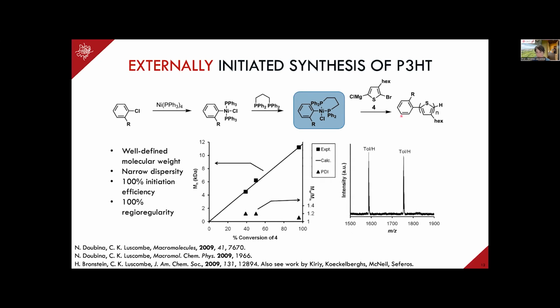And this allows us to really synthesize polymers such as P3HT in an extremely controlled way. So the benefits of doing this polymerization is that we end up with very well-defined molecular weights. If we target a specific molecular weight, we can obtain it. And this is what this graph is showing. The solid line is the calculated molecular weight that we were theoretically expecting. And you can see the squares are the experimental data points that we obtained.